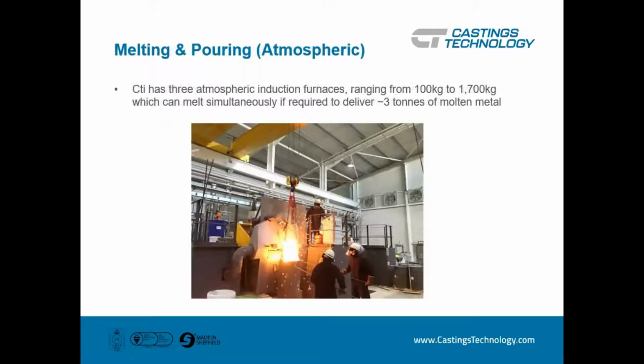And then we're going to melt and pour. In this case, I picked on atmospheric melting because the part, as described, is super duplex. We melt that generally in atmosphere, depending on the specification. And we have a relatively modest melting capacity for steel. We have 3 furnaces, so we're able to make a range of parts without melting too much material, and they're on a single electrical track, so we can melt all 3 at the same time and create around about 3 tons of molten material. Now, because our yield using this process is relatively low, that will give us a finished casting of around a ton and a quarter, something like that. The rest of that material is part of the process. It gets cut off, it goes back into the process and gets recycled, of course, like most metals do, but the yield is relatively low on this process.